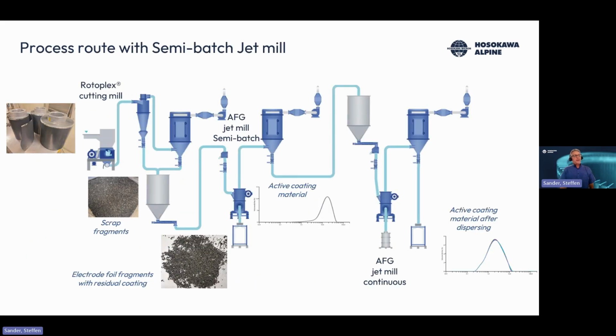We've also shown that there's a bit simpler process feasible by exchanging the combination of the fine impact mill and the classifier with a semi-batch operated fluidized bed jet mill. So you can see the first jet mill here, and of course, again, the fine material, the coating material, is still too coarse to use it directly for the recycling material. That's why, of course, also here a subsequent treatment with a second step is necessary.